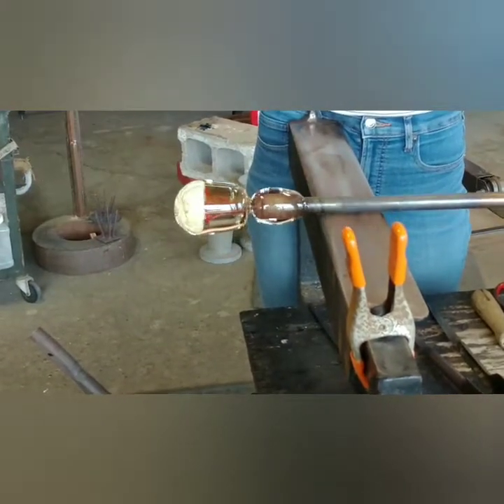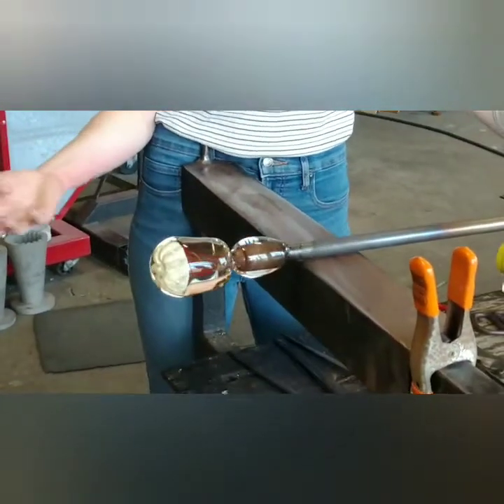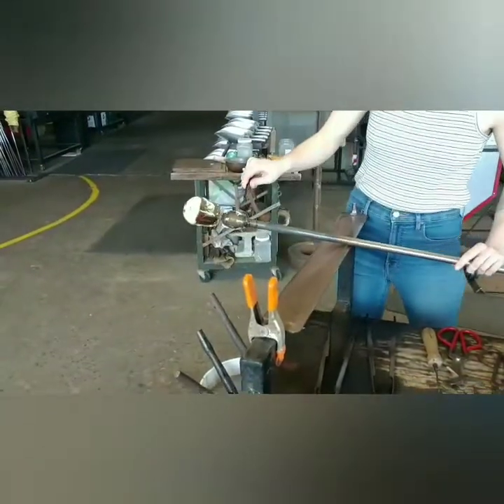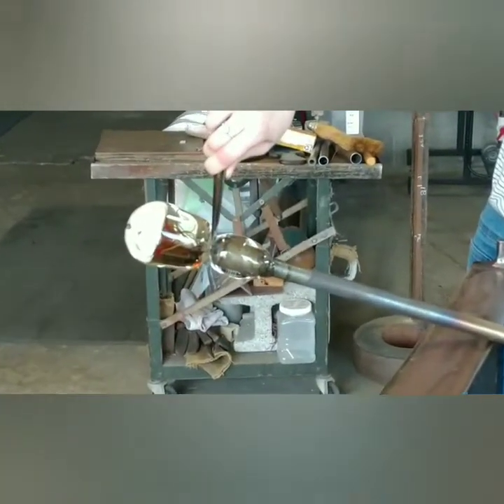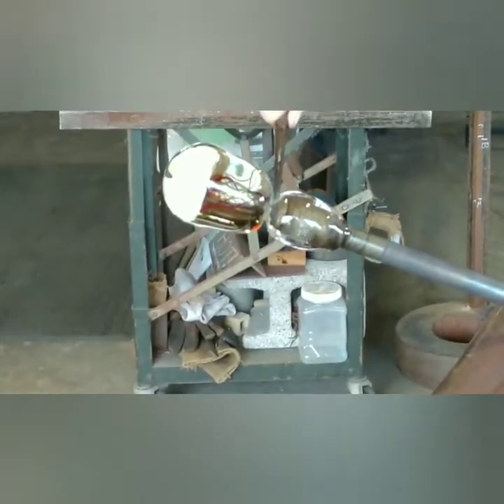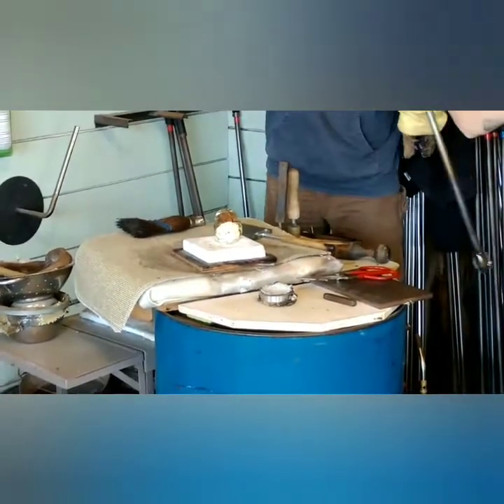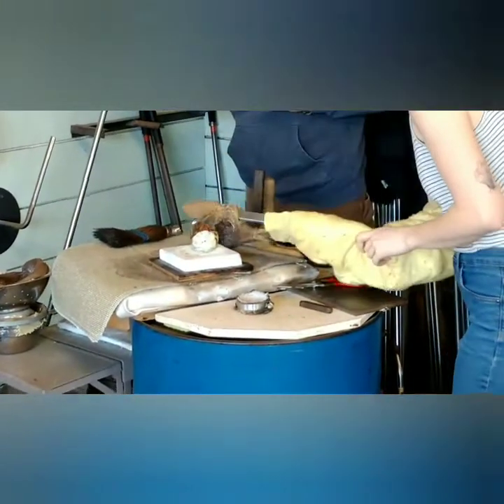You can see it's moving less than it was a little while ago — I can turn a lot more slowly and it's not falling off-center. I'm going to pull it in and crack the glass, essentially micro-cracking it. So I'm just going to put water directly on this constriction line and then cinch down and remove a little bit of glass. Let's try a little spirals and twists — get it a little higher and then try to pinch and twist to create that.